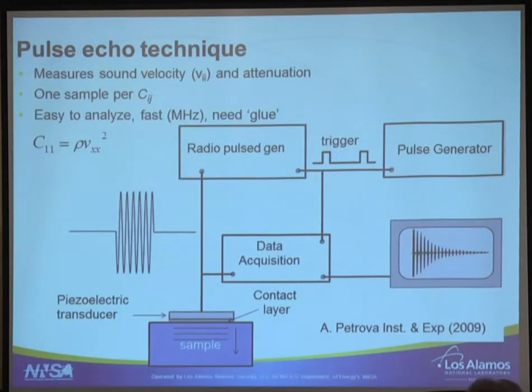The way you do it, a typical pulse echo technique to measure elastic constants, is you have a pulse generator, and then you send a pulse into a sample. To do this, you have your piezoelectric transducer, in blue, your sample, and then you send your sound wave, and you basically hear the echo with the same transducer.